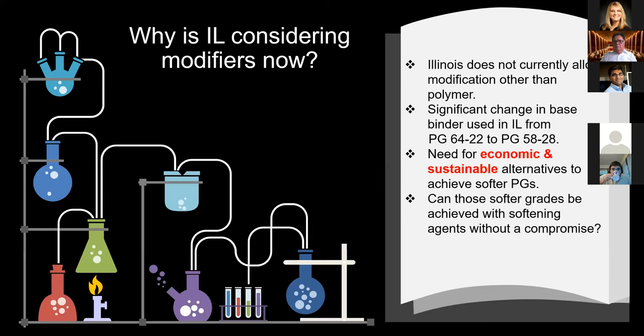The Illinois specifications do not currently allow asphalt binder modification with anything other than polymer. IDOT is now considering allowing other modifiers due to the observed shift of the base binders, as Jim showed earlier in a graphic, from PG64-22 to the softer grades such as PG58-28. These softer grades are being used to adapt to the higher levels of recycled asphalt content in our HMA. The need to change became increasingly evident in recent years. Our industry partners have highlighted the variability of the current crude sources and the overall difficulty they have in achieving the softer base grades without the use of modification.